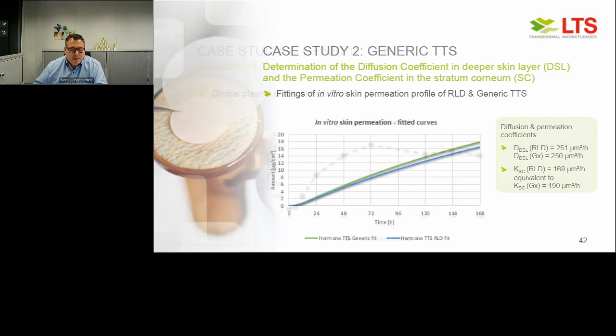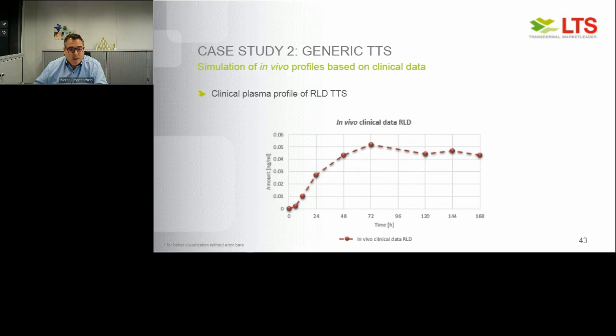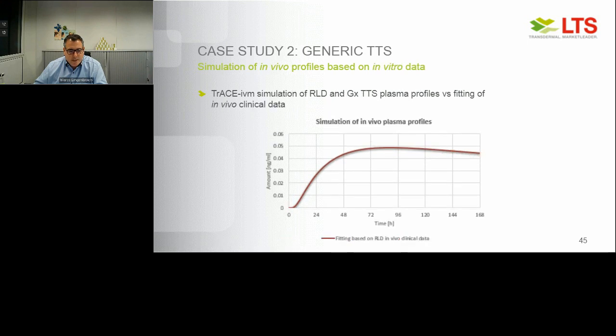And as another parameter, we add in clinical data, which we can find in the literature. This is an example of a clinical profile over application time of this hormone patch. We're also fitting those curves within our software to get all the data out of it. So let's eliminate the actual clinical data, keep the fitting, and for comparison add into this profile a plasma profile simulation of the RLD based on our in vitro data set. We see already a slight difference between our in vitro and in vivo, but for this kind of simulation, it's pretty close and very great, we think.